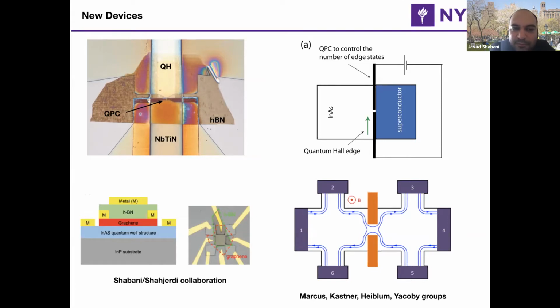I mean, this work hopefully will result in more understanding of what's happening, because now I can only let one mode into a very small area, only about 100, 200 nanometer, and then see what happens in the tunneling regime. In our devices, we have to use hBN because the aluminum oxide changes the density of the 2DEG. So there is some sophistication with it. Something that we started, and I don't know how hopeful I am now, is these bilayers of graphene and indium arsenide that we made devices with independent contacts to see if we can induce quantum Hall in each of them.